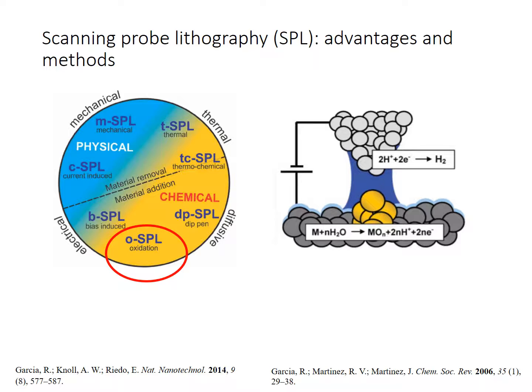By bringing the tip within nanometers of the sample, the layer of water present on the sample surface due to the interaction with the ambient environment will form a meniscus toward the AFM tip. And the sharp tip of the AFM results in a high electric field between the tip and the sample, and this ionizes the water molecules in the meniscus. So the hydroxide ions will then migrate toward the sample due to this electric field, where they can then oxidize the substrate. So here a process model will be developed for AFM oxidation scanning probe lithography, as it has been demonstrated to be more repeatable than the STM method.